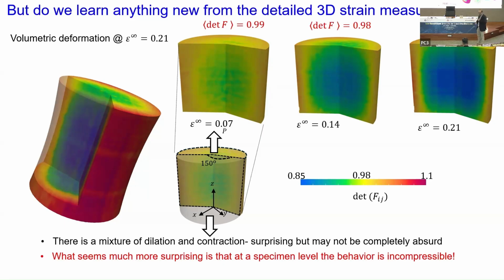I'm now taking the volumetric average of this volumetric deformation over the whole specimen. So this angular bracket means average over the whole specimen. I'm getting numbers like 0.99, 0.98, 0.99. Well, that's within my error. And 1 means no volume change, basically. So what it's telling you is that over the whole specimen, this mixture of dilation and compaction seems to be canceling itself out, and the whole specimen is remaining incompressible.